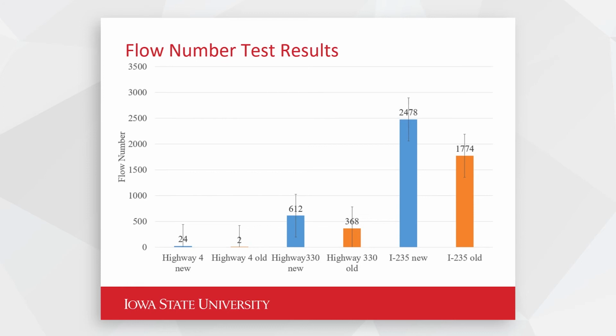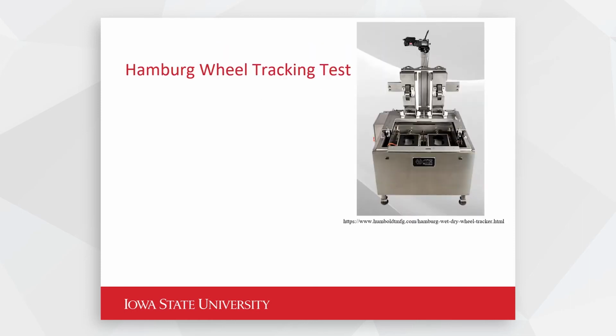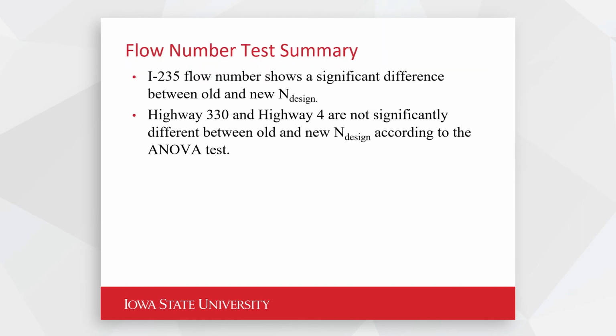And although there's quite a statistical difference on 235, you can see clearly there's a preference for the new design criteria. So interestingly enough, just a tenth of a percent binder change on 235 did lead to quite a bit of improvement in rutting resistance in terms of flow number. So, if we flip through, we have all the analysis of variance and stuff in the report. We next go to the Hamburg device.